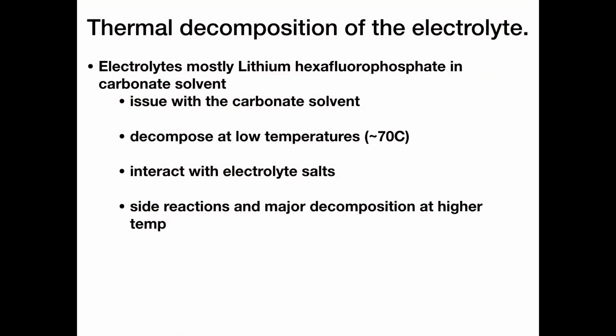Yes. And so at that point, the decomposition of these carbonate solvents, they begin to react with the electrolyte salts themselves. They will react with the lithium instead of the lithium ions getting to the anode or cathode. And so you've got new compounds just completely being formed within your battery, which then creates even more side reactions. And so you got major decomposition.